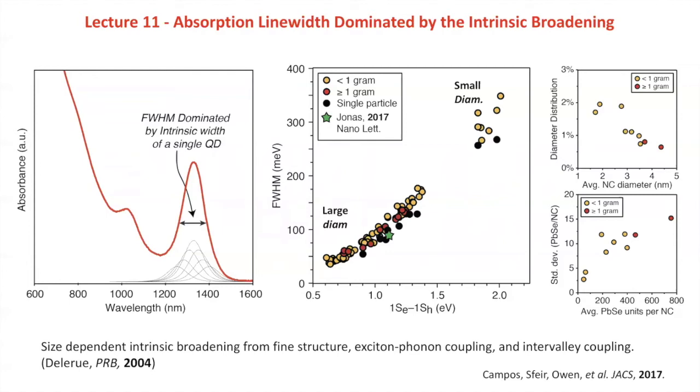And basically, what I'll tell you first off is that the size distributions are almost perfect, meaning that under our conditions, and many other people's conditions, the crystals that are produced have a few percent, maybe 1 to 3 or 1 to 5% size distribution.